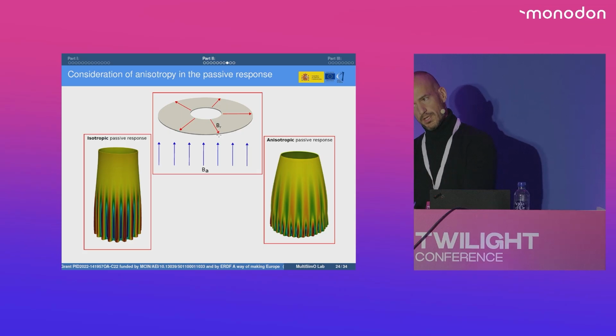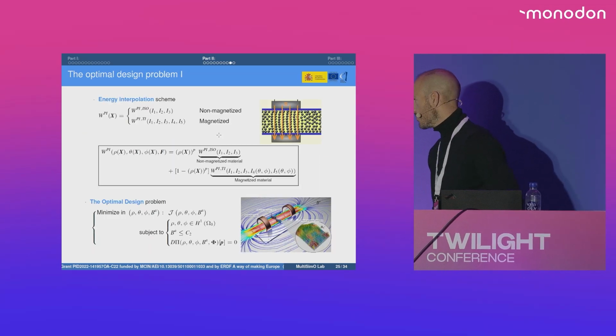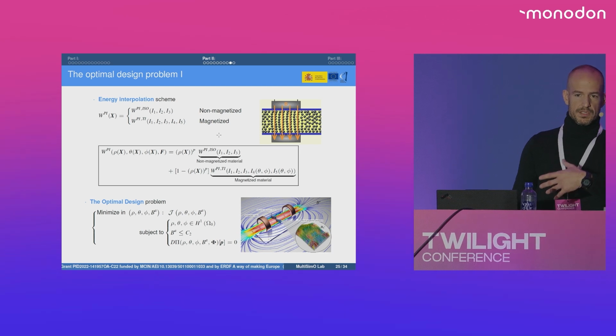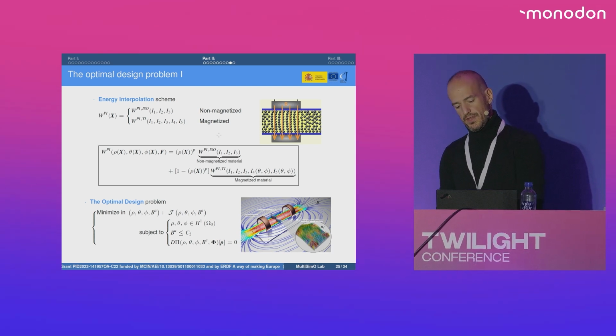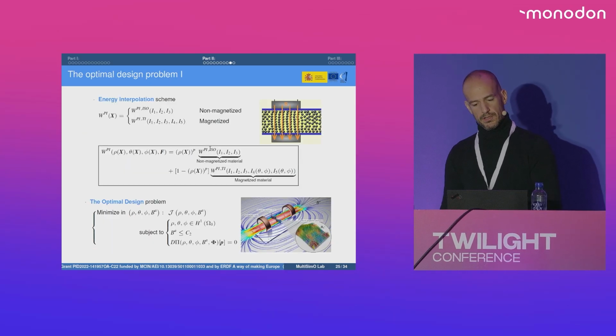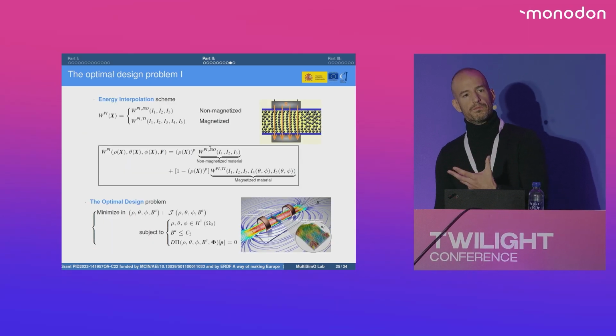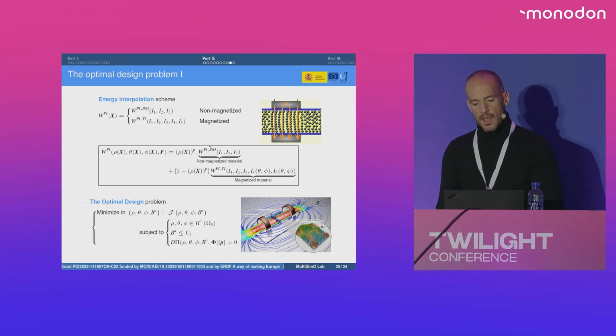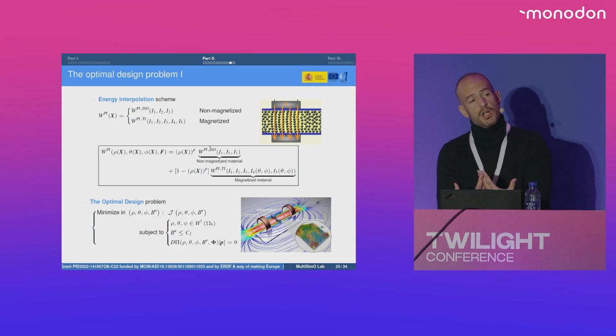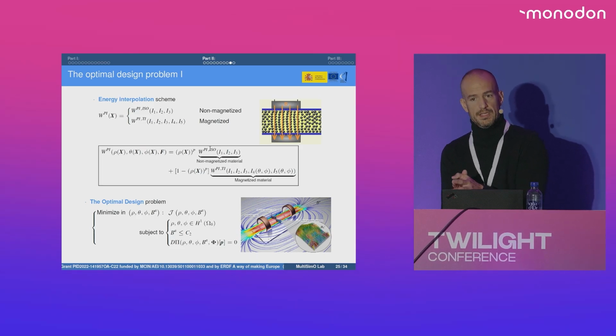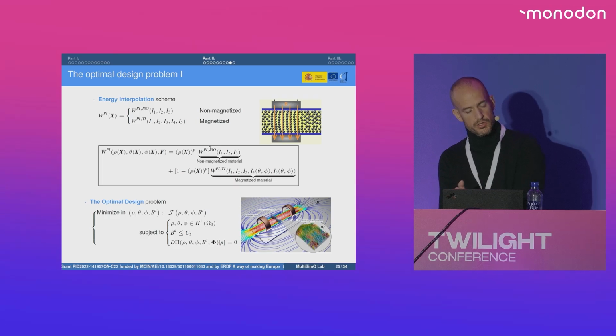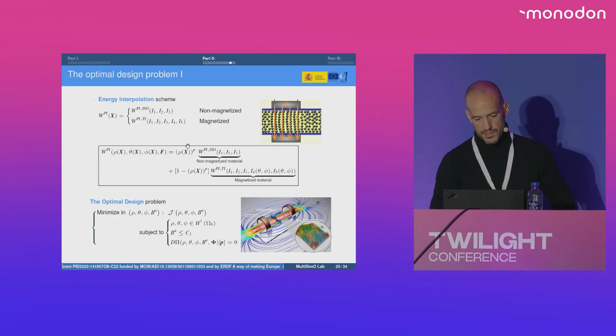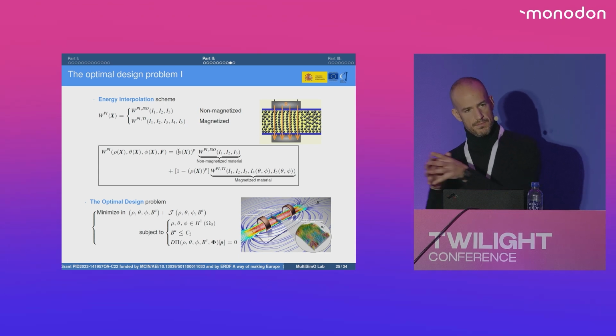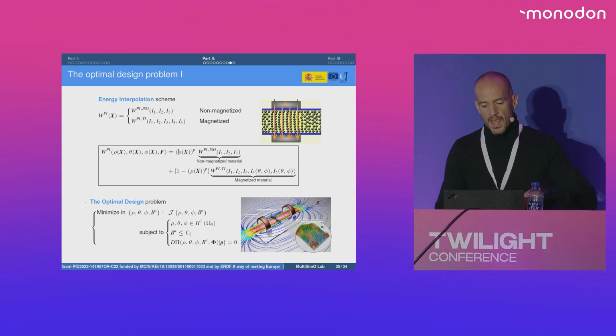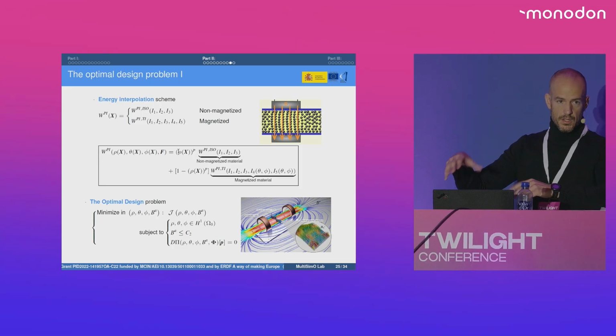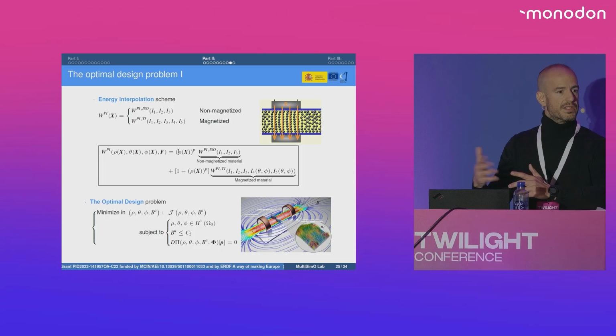So we are capable now of simulating these materials, and we can integrate these into our topology optimization framework. Again, we need to formulate this as an optimization problem. What I want to do is apply this field, this B field, and applying this field on this material, I want the material to move to attain a target shape, okay? According to what? Well, the topology optimization algorithm is going to tell me in what places I need to magnetize and in what places I am not going to magnetize the material, and this is done by introducing this pseudo-density field, which is regulating magnetized and non-magnetized material, and also in those regions where you magnetize the material, in what directions. So the direction of the magnetization is also a design variable in my problem.